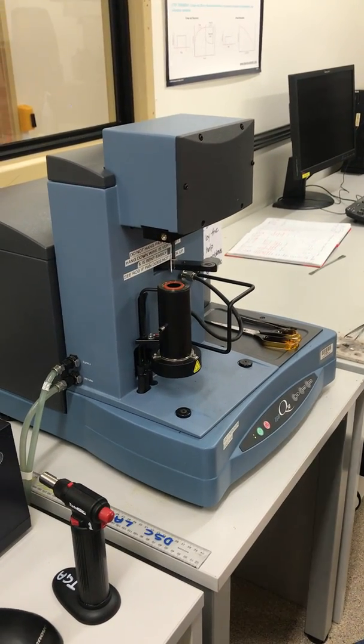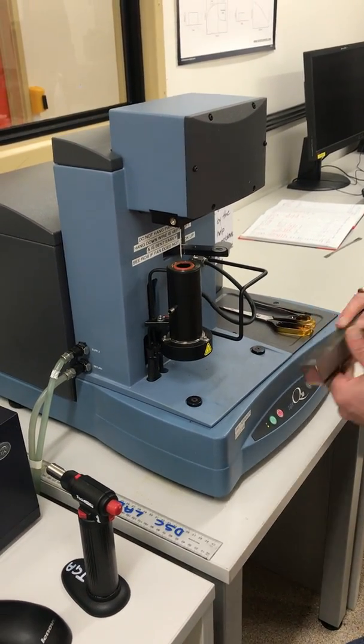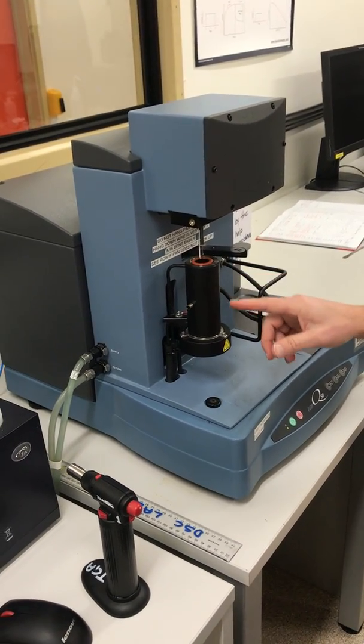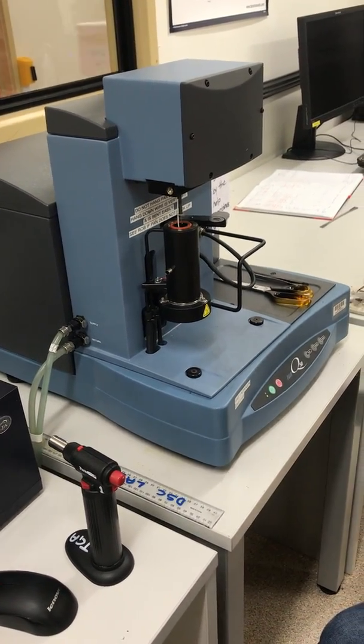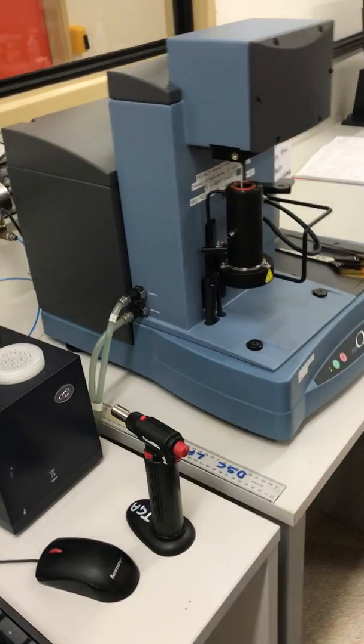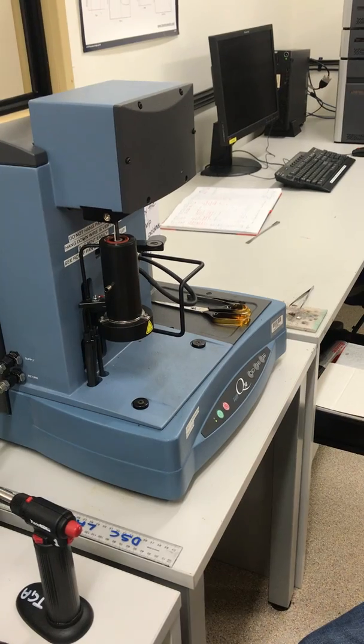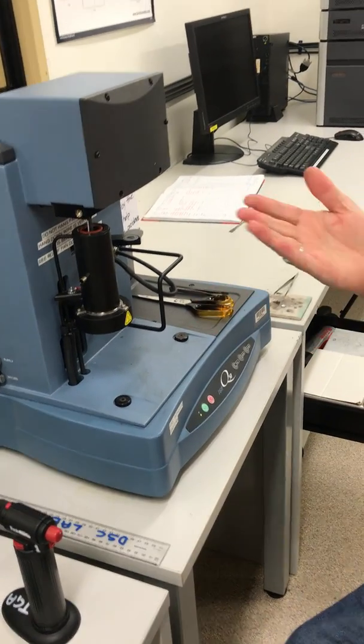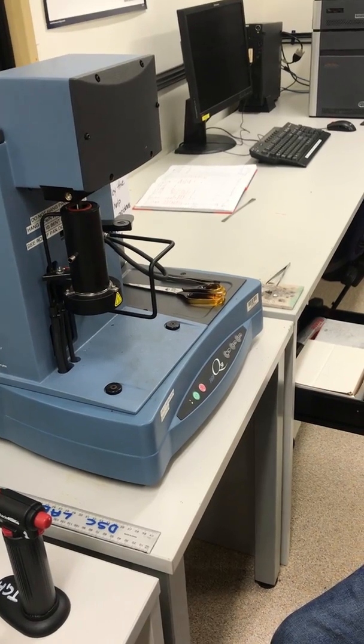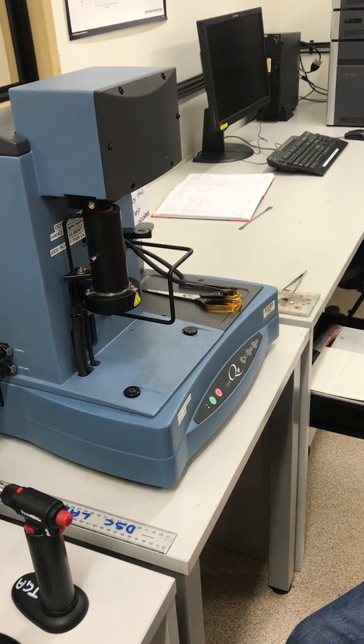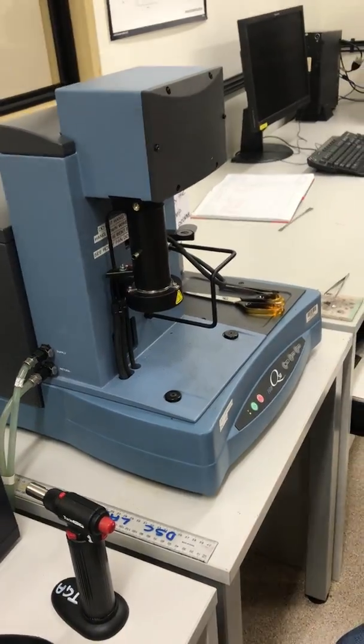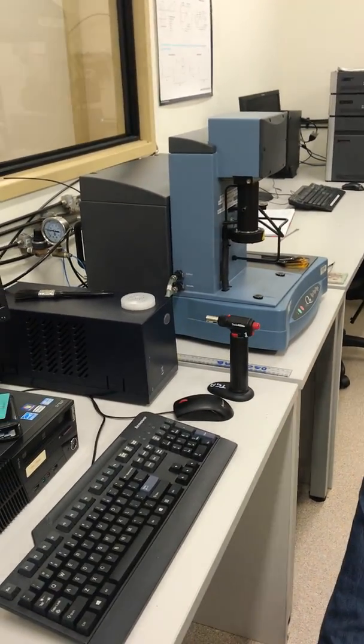And I have a big magnet in here that I put underneath there, right at the base, and when the sample is heating up, it's having an effect on the magnetised nickel sample. When that becomes non-magnetic at around 300 degrees, it lifts up, and there's an apparent weight change, but it's not. It's just a change in magnetism. Oh, okay. So we use that to calibrate the instrument at a good midpoint around 300 degrees. Pretty cool. Yeah, it is. It's unusual that such a high temperature metal has a low temperature Curie point. To reverse that, I can press it again.